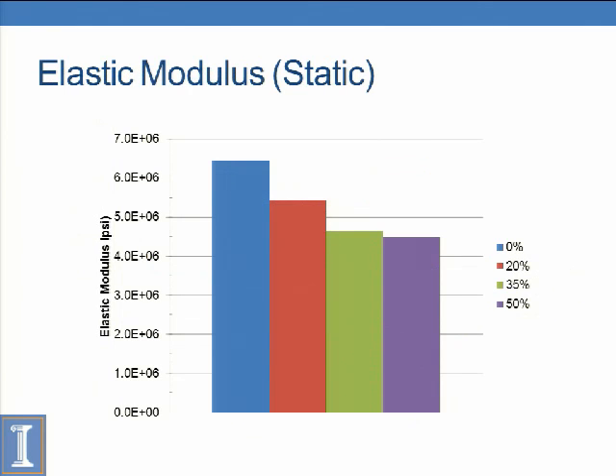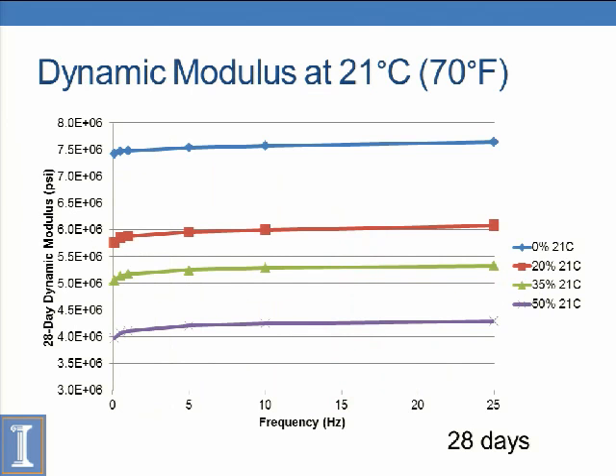Now looking at elastic modulus, this is just a test setup. We apply a compressive strain. You measure with an extensometer, the stress versus strain essentially. And as consistent with the literature, we had a reduction in elastic modulus with increasing FRAP. Similarly, dynamic modulus, we have 0 to 50. We have a reduction in dynamic modulus.